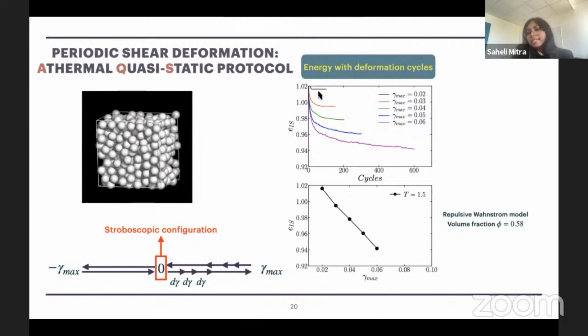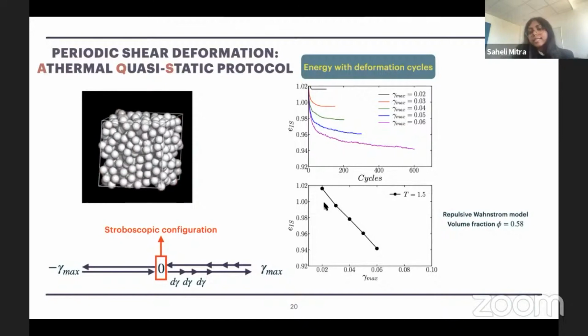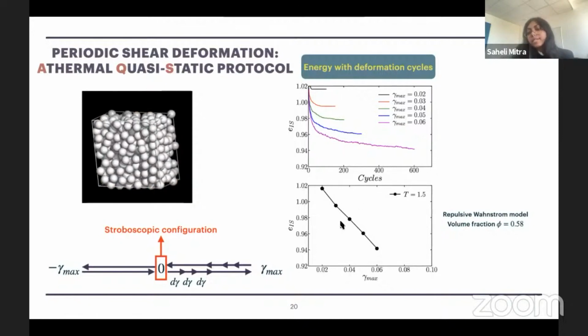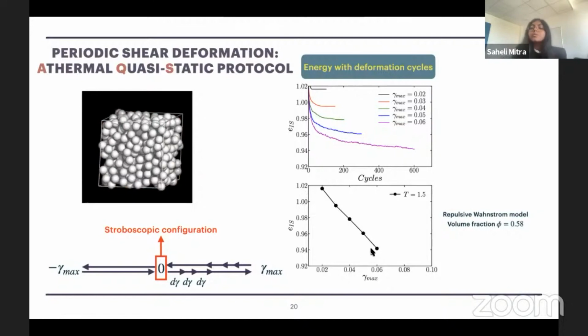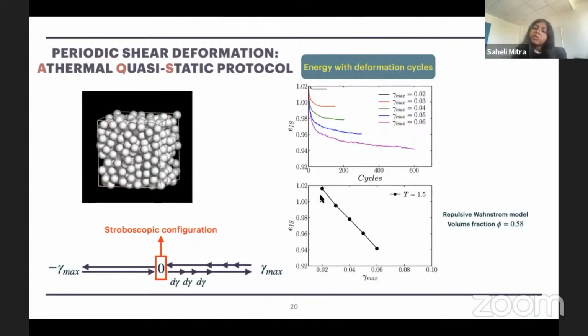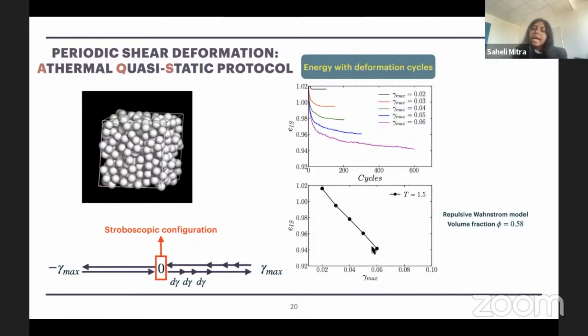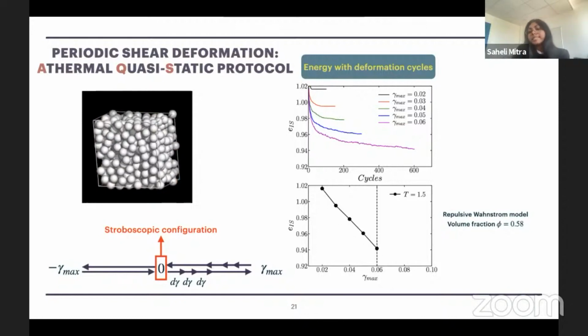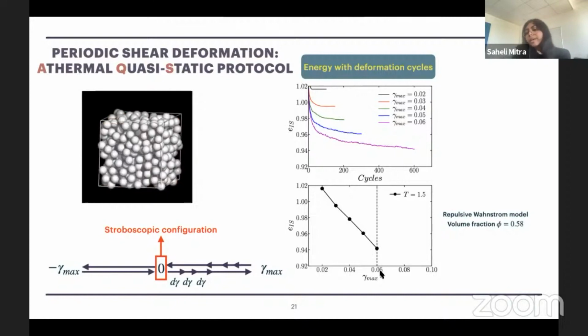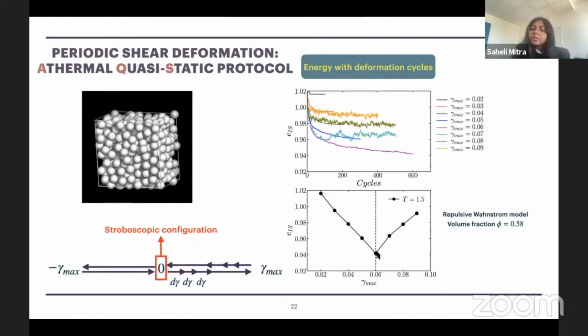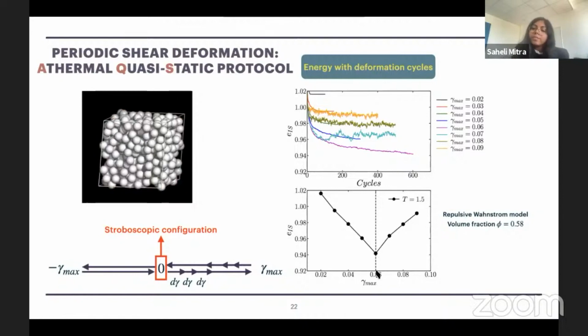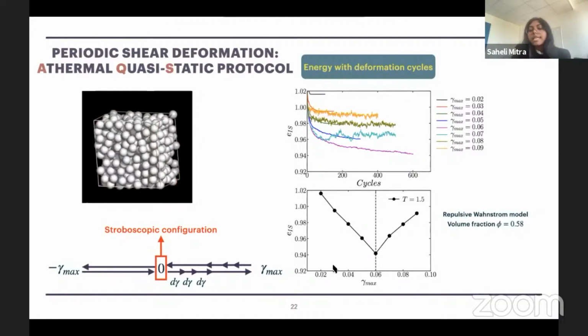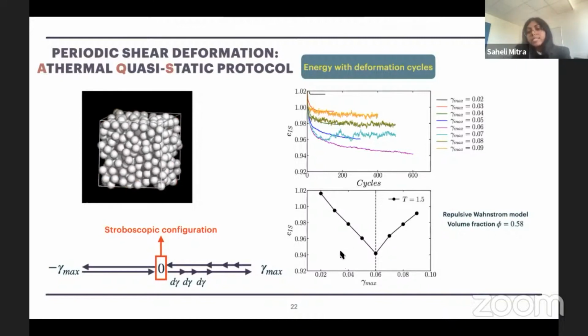So the asymptotic energies of the system decrease as we shear the system. So if we plot the asymptotic energies as a function of shear amplitude, we can see this decrease of energy. So the glass system now explores deeper energy minima as we are shearing the system. This is known as mechanical annealing in glasses, and this keeps on happening until the system is yielded. Once the system is yielded, if my strain amplitude is high, then there is a sharp jump in the energy, and this sharp transition from the states below yielding and above yielding is quite clear from this energy plot.